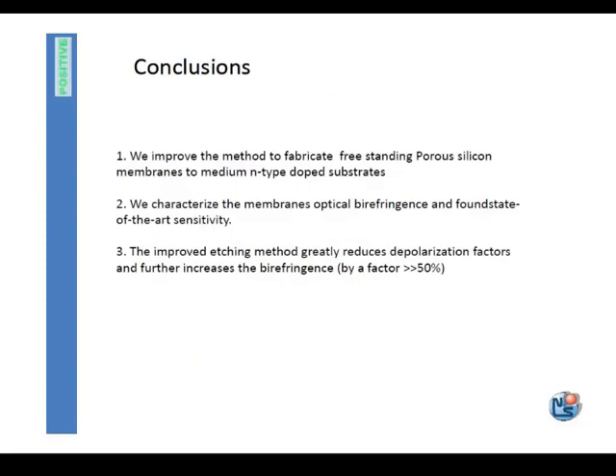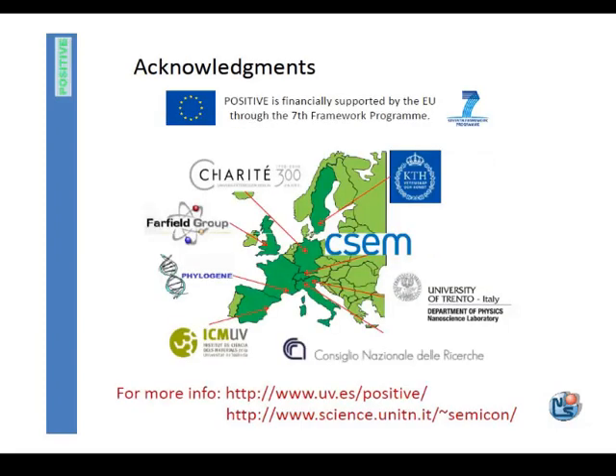So, the conclusion: we have improved the method for fabricating freestanding porous silicon membranes, and we show that it's possible to obtain very thin, high-quality membranes also on medium n-type doped substrates. This is the first time people have created this type of sample. We have characterized the membrane's optical birefringence and found state-of-the-art sensitivity. And we achieved this nice result because we improved the etching method, and we are able to greatly reduce the roughness that in turn reduces the depolarization of the sample.